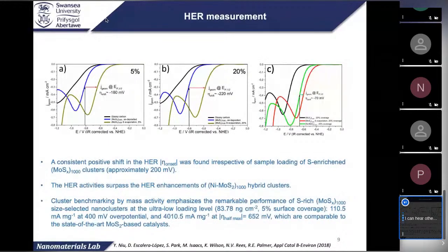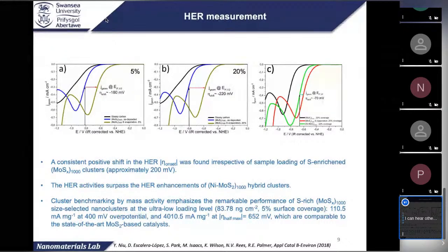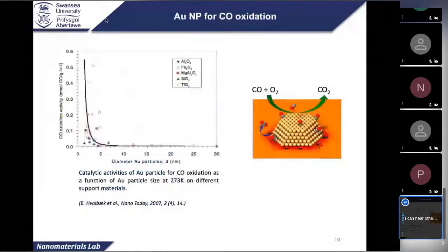So basically, we found that the crystallinity helps to improve the electrocatalytic activity, and the sulfur addition helps as well. So this is what we found with these clusters. And then we did cobalt, but it's not shown here. So I'll just give you another example of gold particles for CO oxidation.